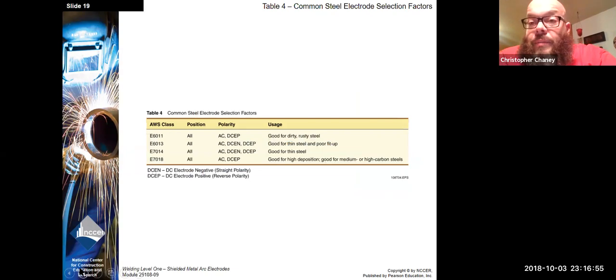All right, here's just some selection factors. When we look at electrodes, these are common steel electrodes and their selection factors. We have 6011. It's an AC or a DC electrode positive polarity. It's good for dirty, rusty steel. 6013, good for thin steel and poor fit up. 7014 is good for thin steel. 7018, good for high deposition, good for medium or high carbon steels. So this is just kind of some different uses.